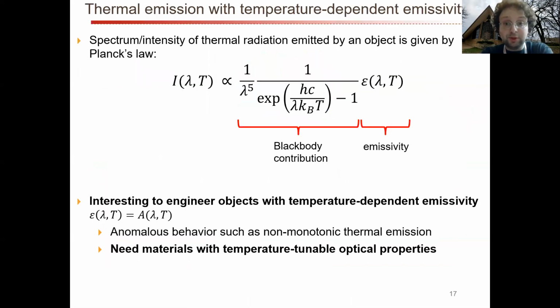Okay, so now I want to talk a little bit more about engineering of thermal emission rather than sensing or metrology. So the spectrum of thermal radiation is always given by this blackbody contribution multiplied by this emissivity, assuming that your emitters are in equilibrium. And this emissivity, again, can depend on many different parameters. And one of those parameters, the one that we've been interested in our group for a while, is temperature. So it's quite interesting to engineer objects with temperature-dependent emissivity. So for example, the emissivity, which is equal to the absorptivity, depends on temperature in a way in which you now have two terms, this term and this term, that are both temperature-dependent.